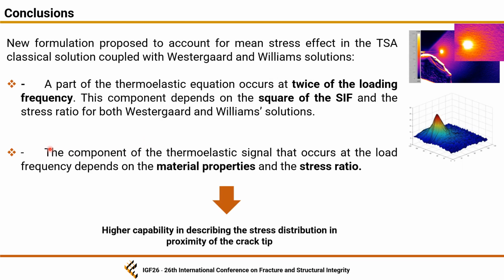Finally, in this presentation, we propose a new formulation to account for the mean stress effect in proximity of the crack tip on materials such as titanium and aluminium. The proposed equation can be a useful tool to understand the limit of applicability of classic theory and well-known solutions, and the error made in neglecting the second order effect.